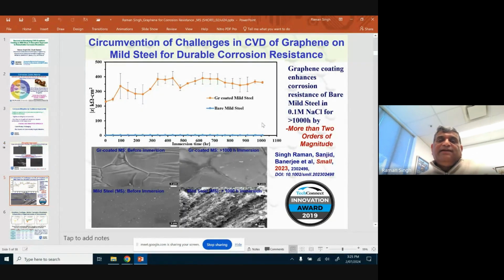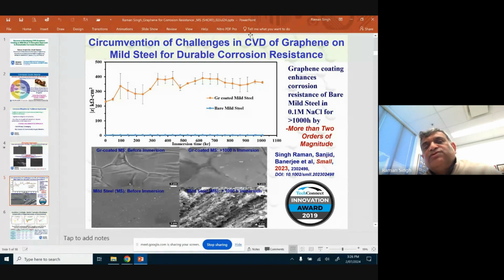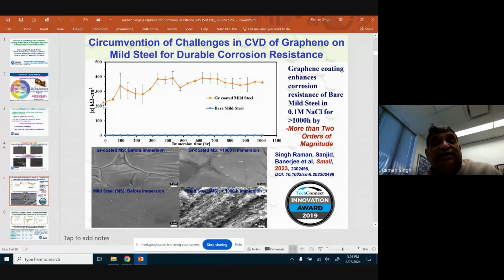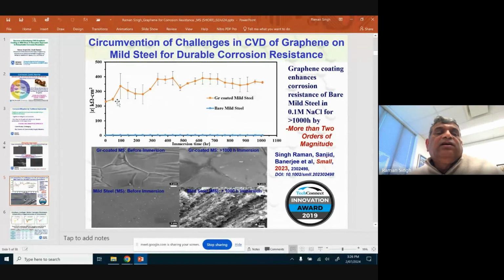As I said earlier, it is very challenging. It is in fact scientifically prohibitive to develop graphene on mild steel. And the good news is that with some intelligent surface modification, we have been able to develop graphene on mild steel, which gives corrosion resistance once again in a seawater type of situation for 1,000 hours or more. And for the reasons that I will talk about in a sec, there is no reason why this corrosion resistance should not be everlasting.